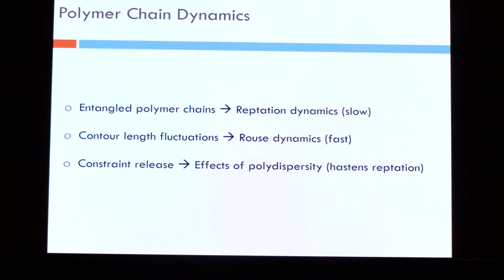If the smaller chains move out, then the ultra-high is able to relax faster. So the tube itself relaxes before the polymers can relax. So the tube helps the polymer to relax. That is called constrained release. It's a two-body problem, and that actually accounts for the effects of polydispersity.